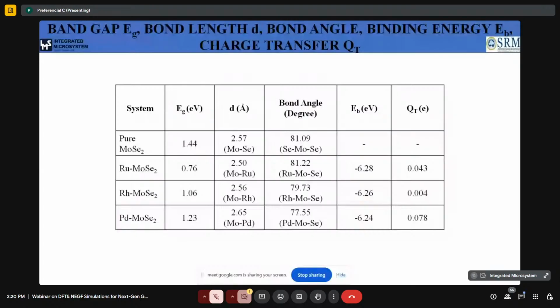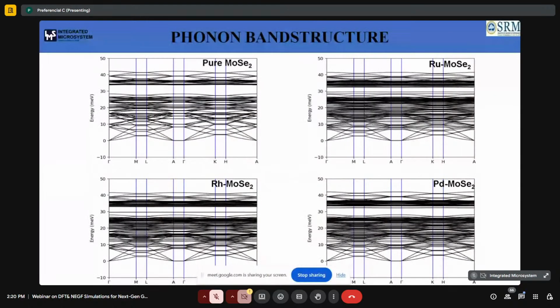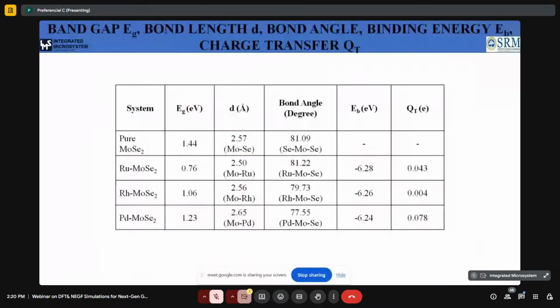In addition to the formation energy analysis, we have also done the phonon band structure analysis to confirm the dynamic stability of the system. In all phonon band structures, only positive phonon modes are seen across the Brillouin zone, which implies the dynamic stability of the system. There is a considerable variation in the structure, but after incorporating the dopant, the system is stable, and that was confirmed.